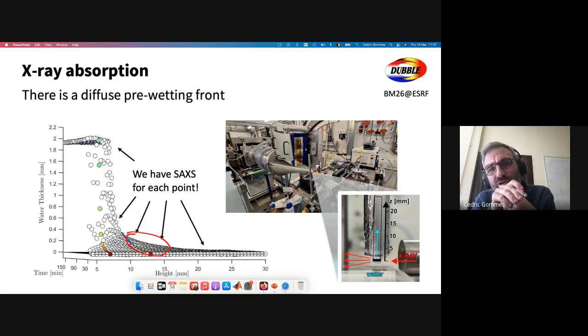And in the case of drug encapsulation, if you have, for instance, solutions, then I gather the relevant contrast would be between the water with drugs and the pure water. And that might be difficult to pick up in scattering experiments. Right. But for instance, in some other experiments that we did, we still have to process them, with the same capillary rise experiments with electrolytes, so basically salt in there.